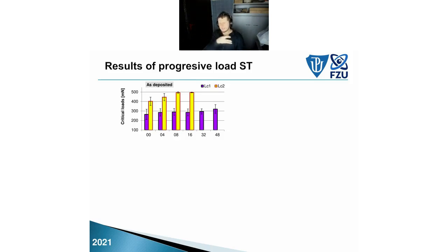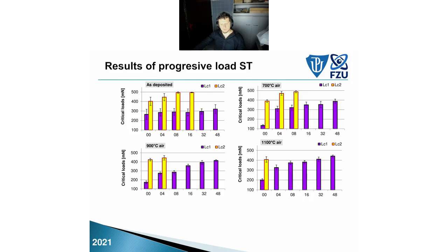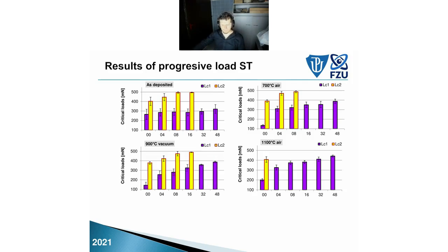Some of the same data is shown here in graphs of critical loads. We don't have LC2, we don't have delamination for higher nitrogen content in the as-deposited sample. And after annealing, we see that LC2 is not happening even at lower concentrations of nitrogen. And we also have an increase of LC1, the first point of cracking. So here are some results from vacuum annealing, which show that even after vacuum annealing, there is some increase in LC1, which means the short range ordering increases the mechanical properties.